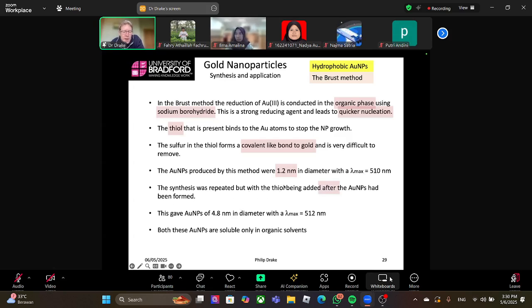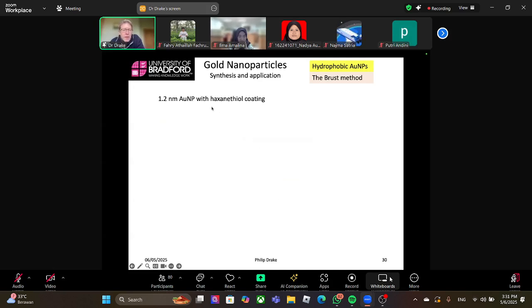We can do the same synthesis, but we can add the thiol later. If we add the thiol after the sodium borohydride, you make the particles and you then grow them into bigger particles and then add your capping agent. You can get about 4.8 nanometer particles. Still small, you still have sodium borohydride, there's still lots of nucleation, so you get small particles. So by using a thiol, we can control very precisely the size of the particles, either having it in the beginning of the reaction or adding it at the end of the reaction. And these are organic solvents. So these are soluble in toluene, in chloroform, in hexane.